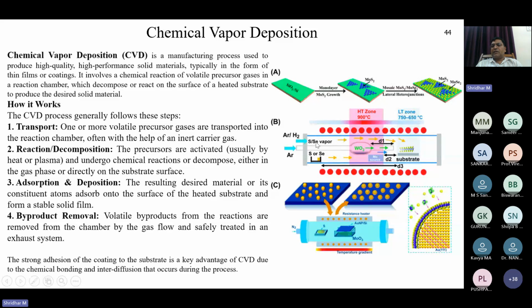And sulfur or selenium vapor they pass, and it reacts with this one, and the molybdenum source metal will be there, and all these materials will react and form MoS2 on this silicon oxide or silicon substrate. You can see here the formation of mosaic MoS2. Mosaic means tile-like structures, MoS2, MoS2, MoS2 on this substrate.